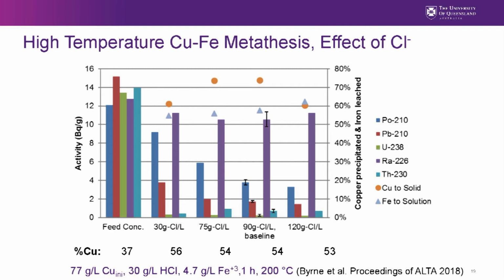So you can see that the initial radionuclide load is around 12 to 15 becquerel per gram per radionuclide. And then we do the metathesis, and the thorium and uranium drop right down at essentially all conditions. The radium didn't change very much. The lead was significantly reduced, and the polonium was reduced a little bit. But this is the polonium here, and polonium decreases as a function of increased chloride, and so does lead. Okay, but radium is relatively unaffected by chlorides for this scenario.